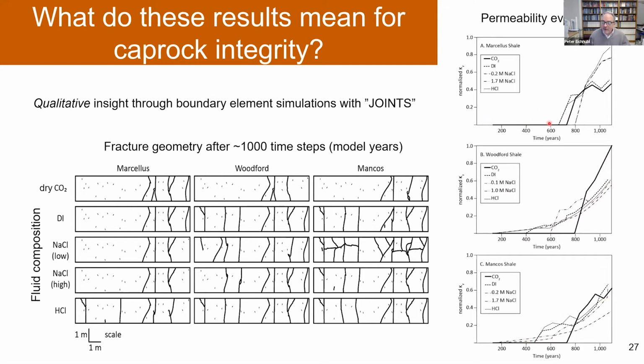In the Marcellus case, the water effect is not so pronounced, but the first thing that actually starts is the HCl fracture. They start here, and then under HCl environments, so highly acidic environments, which is actually more acidic than the CO2 would ever be in the subsurface, you get the highest permeability. So the fracture behavior is dependent on the fluid chemical environment. It affects how much permeability at the end, but it also affects the timing. When do the fractures start growing, and at what rate do they grow? Okay.